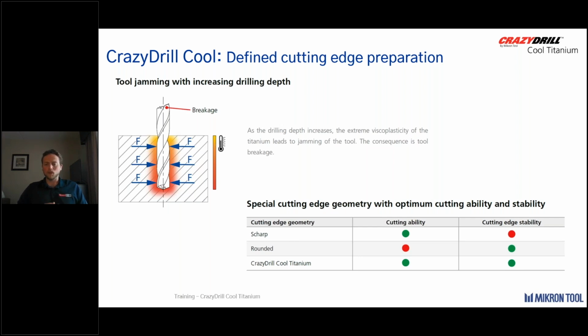But the consequence of drilling deeper is you have that possibility of increasing torque, having chips be stuck in the bore, or having the material actually shrink upon itself, right? As you're drilling, you're transferring heat to the tool, the chip, and the material of the workpiece itself. If you add heat to the workpiece itself, typically you're going to see an expansion of that material, right? The case is the same in titanium. If you add heat to the material, you'll see a slight expansion.